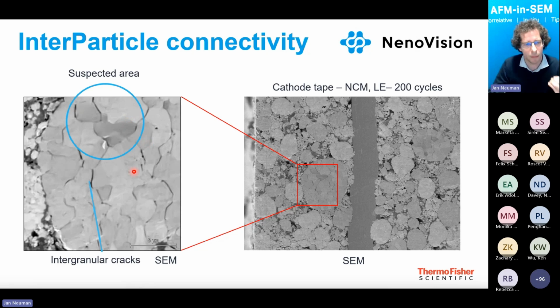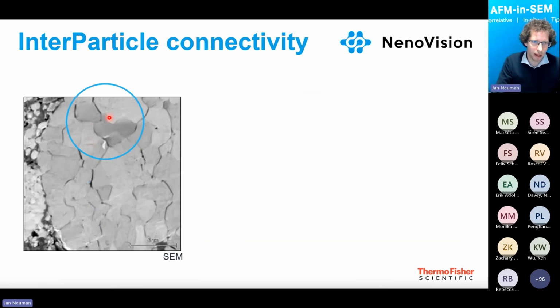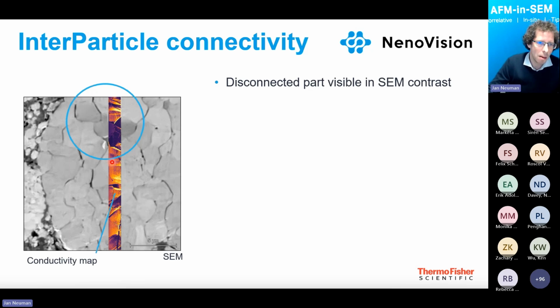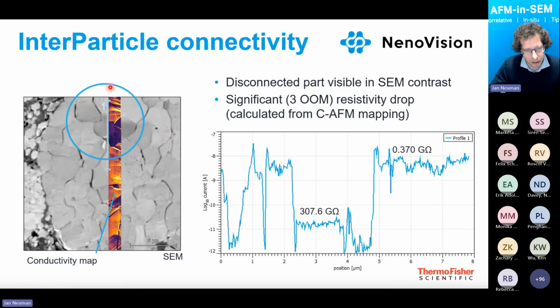And I'm coming back to the question of how much these cracks affect the interparticle connectivity. What we can do for that is again use conductive AFM, measure the conductivity, and clearly see the difference in the conductivity in this region. If we plot and make a profile of the conductivity, we nicely see regions with again 3 orders of magnitude difference in the resistivity. So we talk about 300 gigaohms compared to 0.3 gigaohms. So this is not negligible and it's not an error. This is a fact. And actually, this technique reveals, identifies, and localizes the particles which are disconnected from other areas.